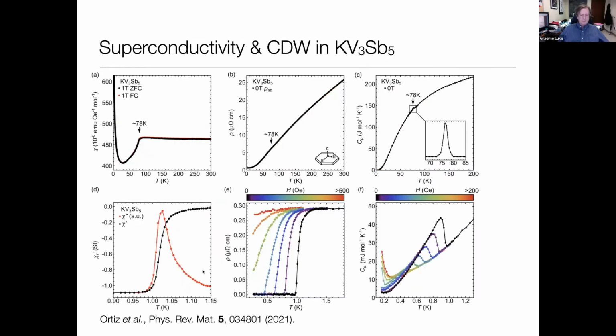They followed on with this. They had already made the materials. You can change the cesium into potassium, and you also end up with a superconductor, with a slightly lower charge density wave transition temperature. If you squint hard at the resistance, you can see a little kink there, and the same with the specific heat, you can see a little feature there. You see a bulk superconducting transition in this material at around 1 Kelvin, which you see in resistance, specific heat, and magnetic susceptibility.